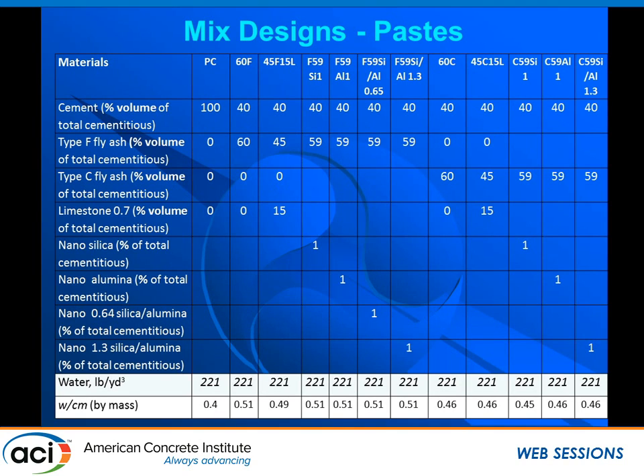We have several mixes. We have a PC mix that was based on one of our concrete mixes from the previous study. We replaced by volume, and we kept the volumes constant. That's very important. So we replaced the cement content by volume by 60%, using either F fly ash or C fly ash, or a combination of fly ash and 15% limestone, or fly ash and 1% of different nanoparticles.